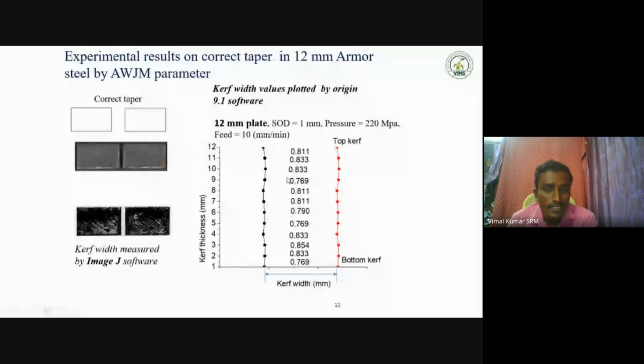Using ImageJ software, I measure the gap: the initial value at the first 1 mm thickness, then the second mm, 3 mm, 4 mm, 5th mm, up to 12 mm. I measure the individual values, then draw the graph. This is the kerf width, the kerf thickness. At the first mm thickness, the value is 0.769. It looks like a straight cut, but in the graph it is not a straight cut. Some oscillation is there.